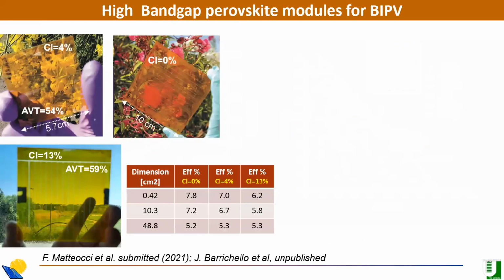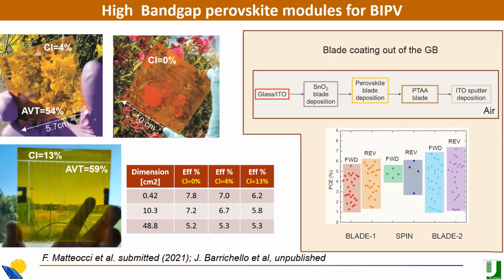You can scale this up to large area. You can see here modules made with perovskite materials with different concentrations of chlorine, and this is quite large area. Scaling up does not reduce the efficiency of the solar cell too much. For example, for the more transparent one, from a small area you get 6.2% efficiency. On larger area, you can get 5.3% efficiency with a transparency which is almost 60%.